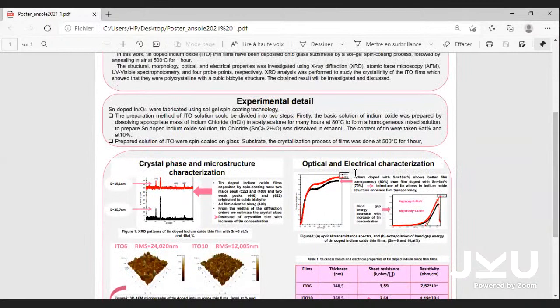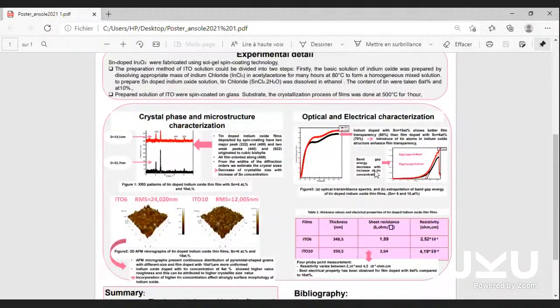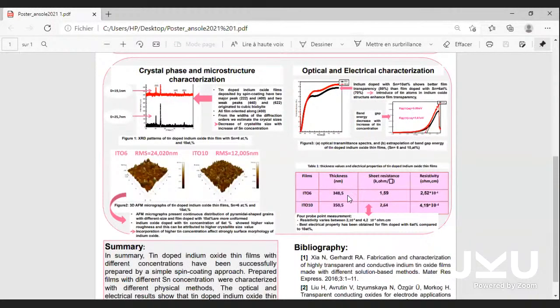For optical properties, indium oxide doped with 10% of tin concentration showed better transparency of 80%. The introduction of tin into the indium oxide matrix enhanced film transparency. Band gap energy decreased with the increase of tin concentration. Electrical properties were studied through four-point probe measurement. The resistivity varied between 2.10 power minus 4 and 4.2 10 power minus 4 ohm centimeter. The best electrical resistivity was obtained for the film doped with 6% compared to 10%.